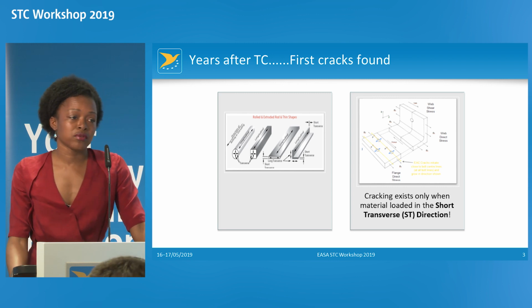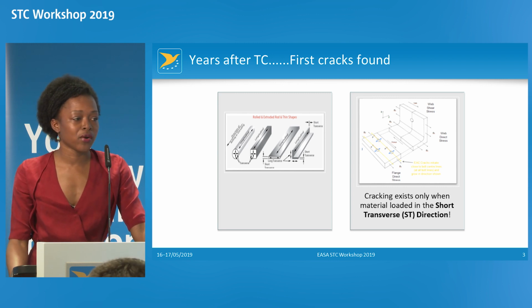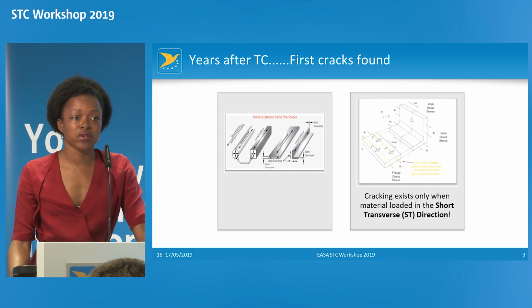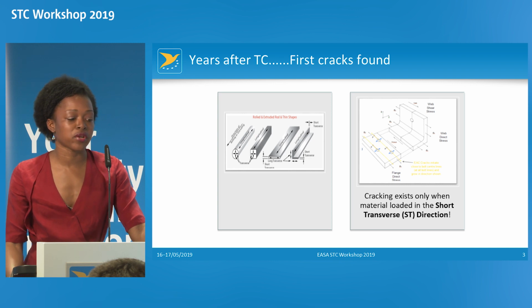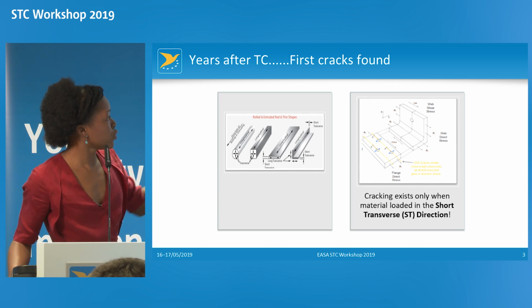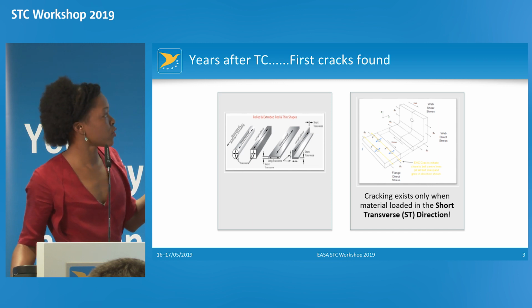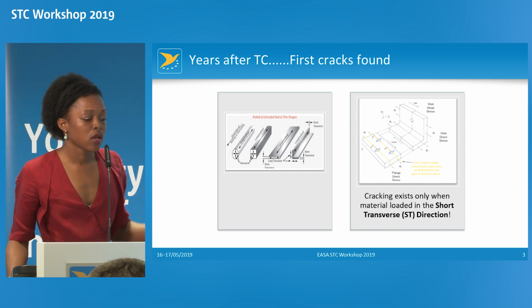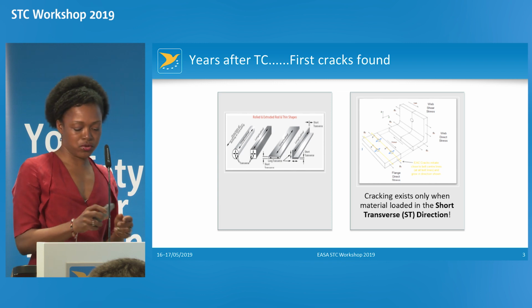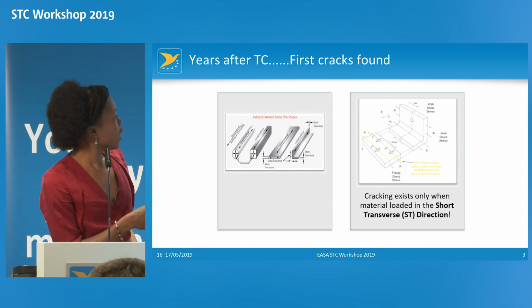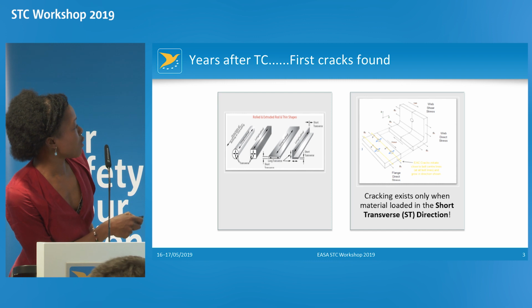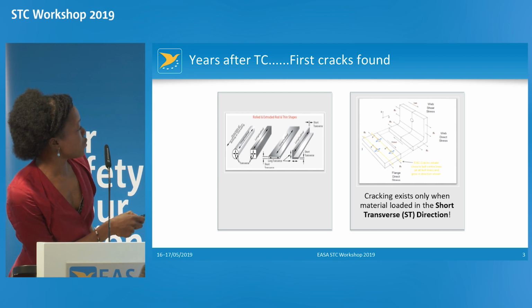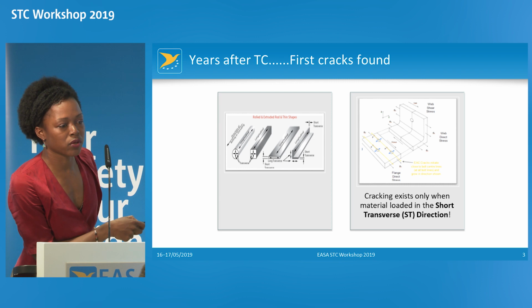Some years after type certification with those alloys, first cracks were found, and they were found in the short transverse direction. On these pictures you have some rolled and extruded rods and thin shapes. On those bars, the short transverse direction is the one that is shown here. On those thin plates, the short transverse direction is basically the thickness direction.